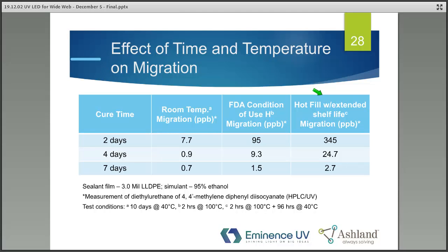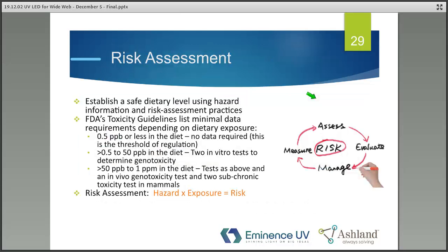But then if you go to this next, which is condition of use H, this is 2 hours at 100 degrees Celsius, so this is boiling water sterilized. You can see the migration does increase because it's the combination of both the high temperature, which was 100 here and 100 here, and the shelf life, because there's an additional 10 days at 40 degrees Celsius. So again, just be cautious of how you set up these tests.